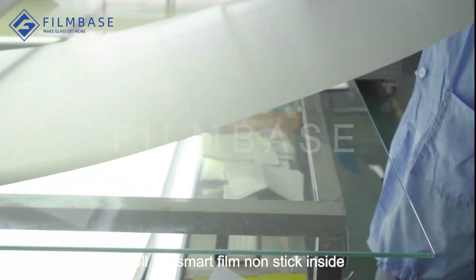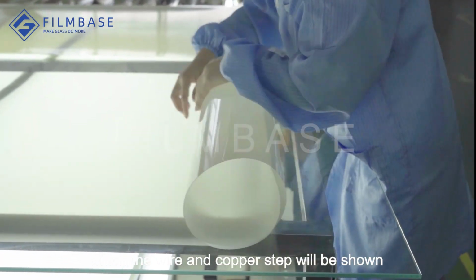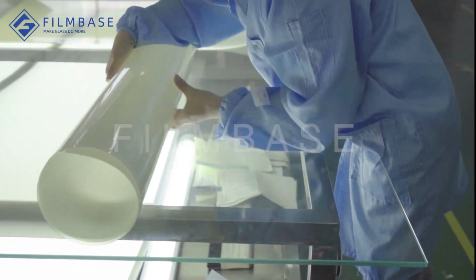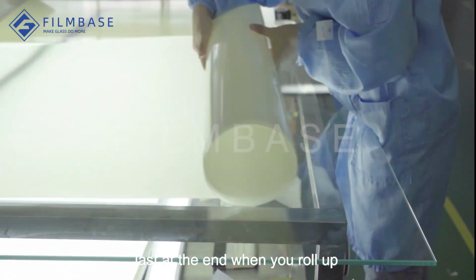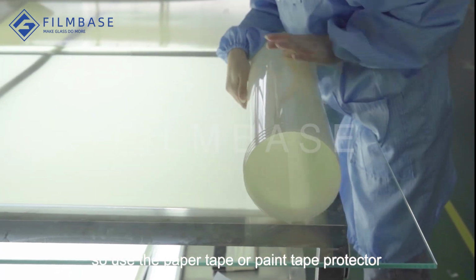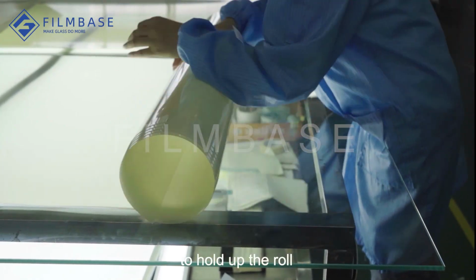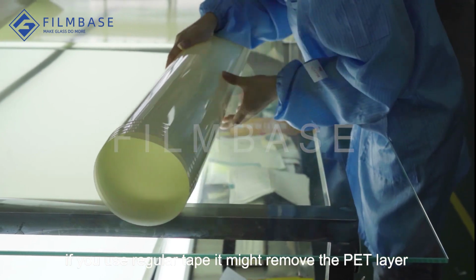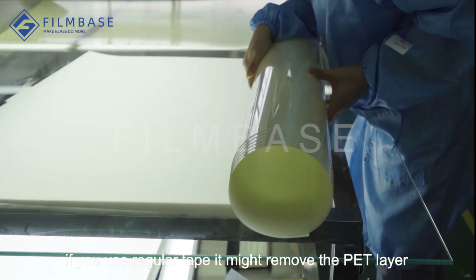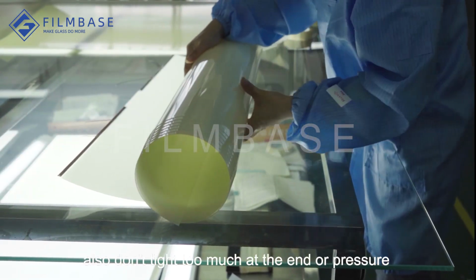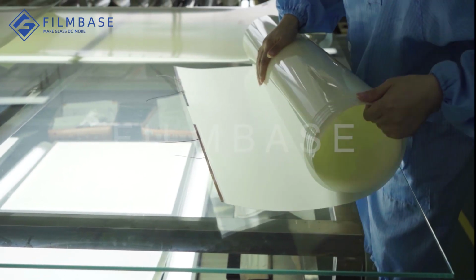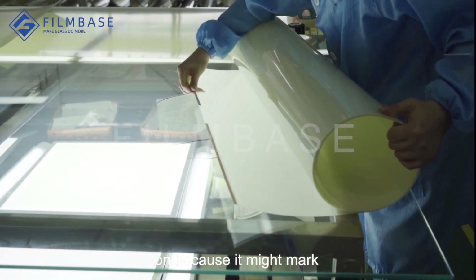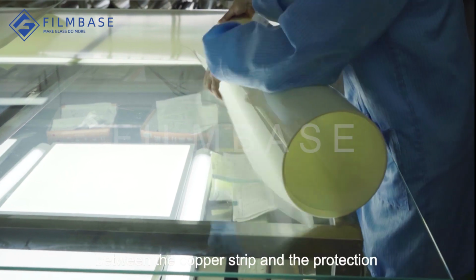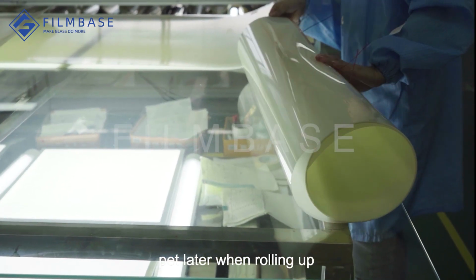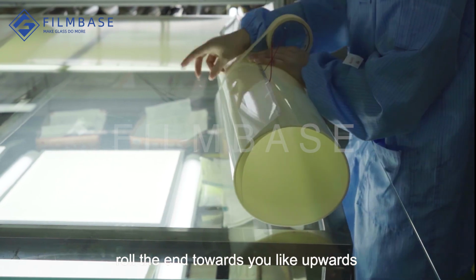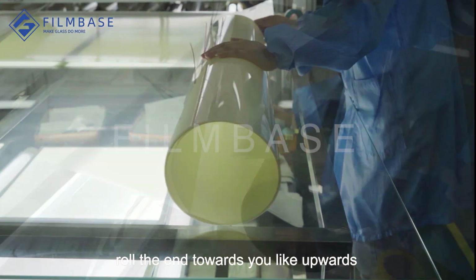Roll the smart film with the non-stick side inside, so that the wire and the copper strip will be shown last at the end when you roll up. Use paper tape or paint tape to hold up the roll. If you use regular tape, it might remove the PET layer when unpacking. Also, don't tie too tightly at the end or pressure the roll, because it might mark or dent the layers between the copper strip and the protection PET layer when rolling up. Roll the end towards you, upwards.